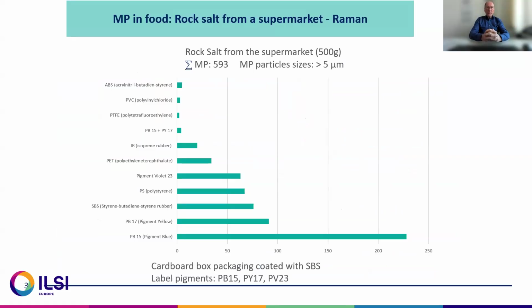Here we investigated a rock salt from a supermarket, 500 grams, and we could identify around 600 microplastics and pigment particles with a size bigger than 5 micrometers. The cardboard packaging was coated with SBS, so it was not surprising that we found SBS in this package. What we also find is a lot of pigments, pigment blue, pigment yellow and pigment violet, and all these pigments are used for the label of the cardboard box. So that means most of these particles come from the production process or from the ambient air.